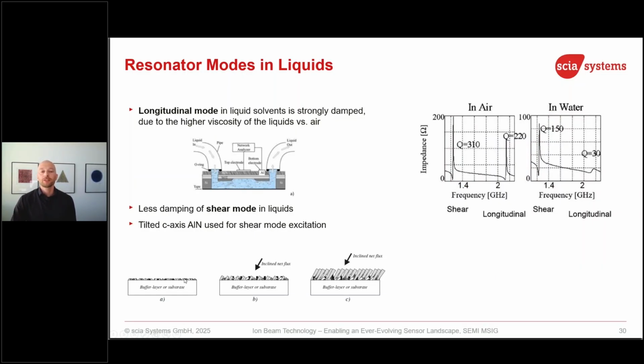So in a normal sputter tool, the wafers are sitting under the magnetron, as I showed before. Particles come more or less perpendicular to the surface, and also your c-axis would be perpendicular. And we need a tilted axis. So how to do it? First, we need a kind of rough buffer layer underneath, and then we have to make sure that our particles are basically coming from the side, not from the top. So the aluminum nitride atoms have to come from the side, and by that we are able to grow the aluminum nitride with a tilted crystal axis.